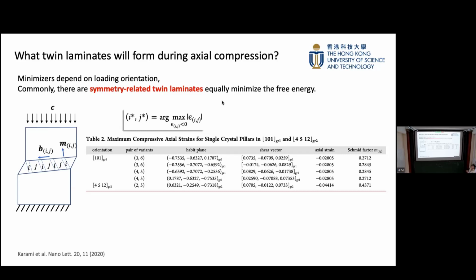Yes. Good question. When you have this sort of situation where you don't have compatibility, like the invariant plane condition is not satisfied, there is this averaging business, and so you get the twin laminate. Microscopically, do you see twin laminates, or are there dislocations there? We see twin laminates instead of dislocations.